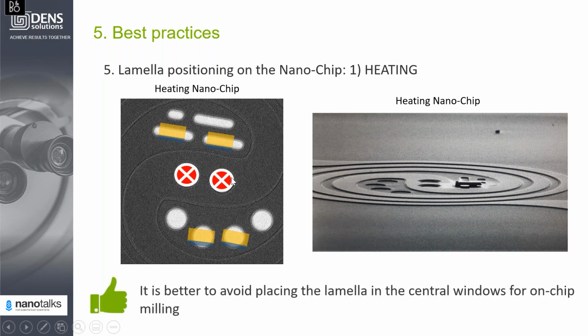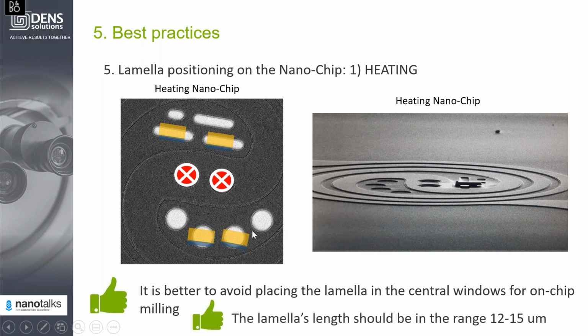If you're going to do the milling on the chip, it's better to avoid placing the lamellas on the central windows. In this case, you might damage the heater. And of course, judging by the size of the window, the lamella length should be in the range of 12 to 15 microns.